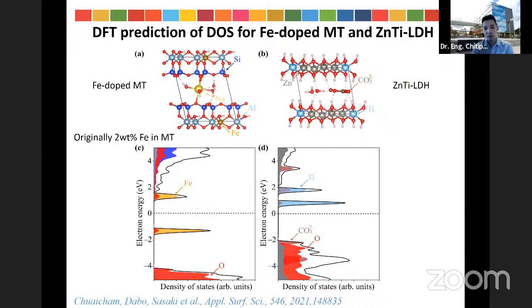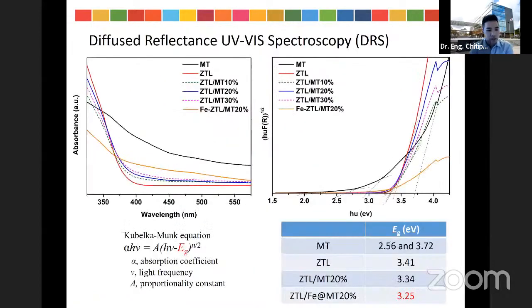So this material can act as an important route to transfer the electron from the MT to the titanium layer double hydroxide. Also, in the titanium layer double hydroxide, the conduction band of this material was contributed by the titanium, and the valence band was mainly contributed by oxygen. So it's clear that when we add more iron into the composite, it can reduce the energy band gap of this material from 3.4 to 3.2 electron volt, which may increase the absorption in the UV and visible light region.